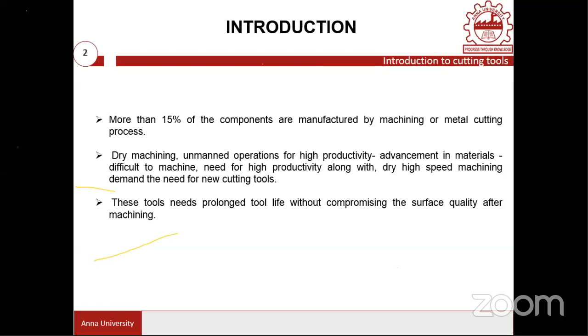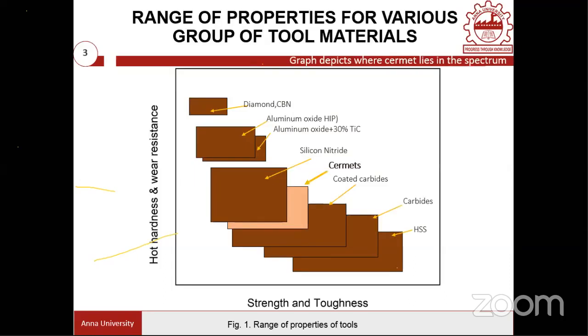So here, as you all know, there are several materials which were developed in the recent past and employed successfully for machining applications. For example, if you take high-speed steel, where the carbon composition ranges from 0.6 to 1.5, along with chromium, molybdenum, vanadium, and cobalt additions, that will give you good toughness, but the hardness value is very, very poor. So they are recommended only for machining ductile materials, where the speed of machining is restricted to 30 meter per minute. It is really a low speed, but still we call this a high speed steel. But the machining capability is still low speed, 30 meter per minute.